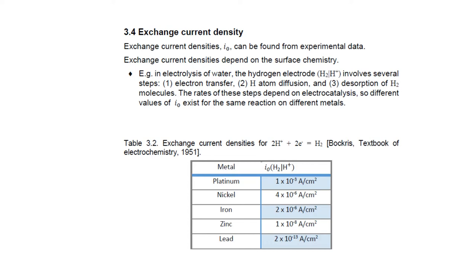And right at the bottom of the table, lead, a notorious catalyst poison, has an extremely low exchange current density for the hydrogen reaction. So lead coatings will frequently corrode very slowly if just the hydrogen reaction is available as an oxidizing agent, simply because it's a bad catalyst for that process. So lead, which only just actively corrodes in many situations, is often a good corrosion-resistant coating. And that's why you can find lead in architecture, and it basically sits there and dissolves at most very slowly. And in other situations, it might just get covered with a scale, and it might be essentially inert or passive.